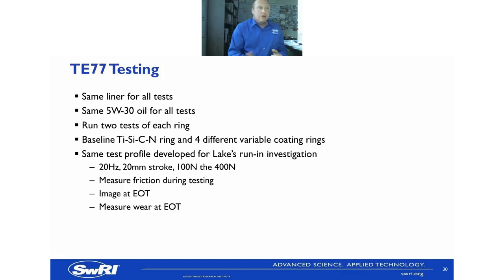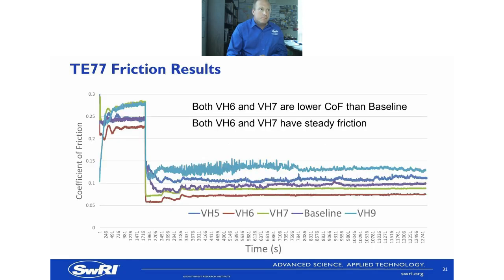So 20 Hertz, 20mm stroke. We start off at 100 newtons and then put that up to 400 newtons. We measure the friction throughout the test, and we have images at EOT and measurement of the wear at the EOT as well. So here are the results.